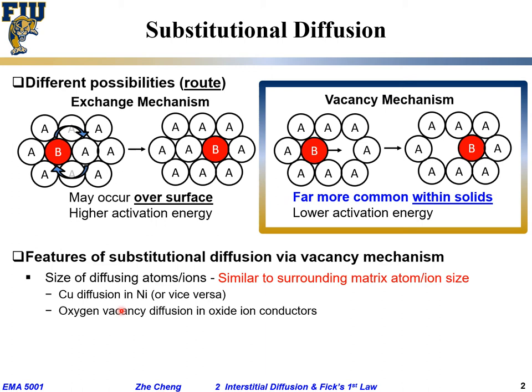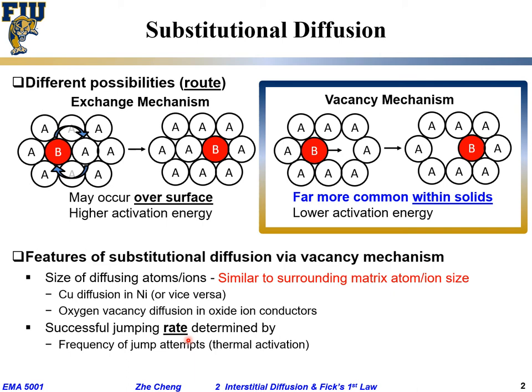And the so-called diffusion elemental step is a successful jump. You see, from here to the neighboring vacancy, we can imagine it as a jump. The successful jump rate, remember kinetics, this class is about mechanism, the route, as well as kinetics, which means rate. How fast or how frequently it can jump, can it happen, is pretty much determined by the so-called thermal activation frequency. Every element, as you learn in thermodynamics, is not sitting still, they would vibrate, they would try to move. Thermal activation. But with only thermal activation, like here, it activates, it cannot really go.